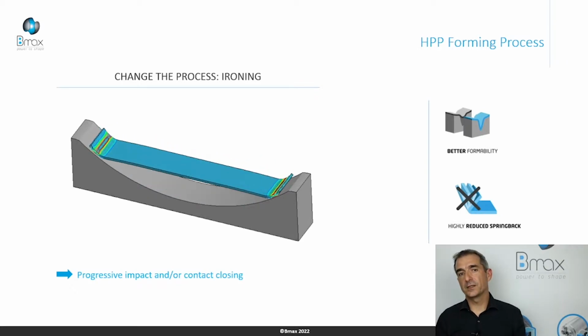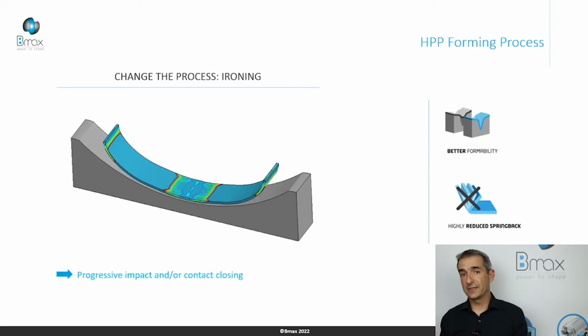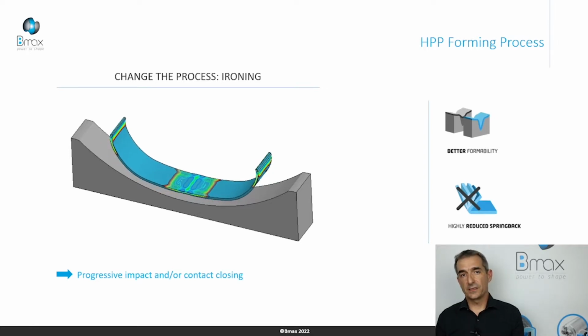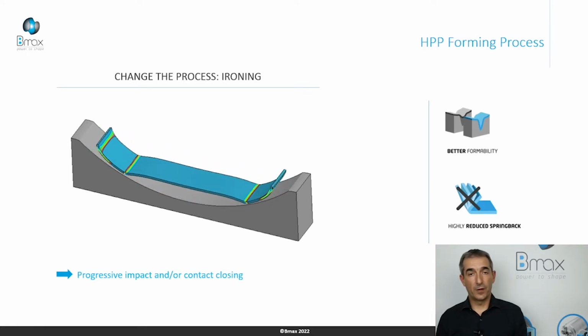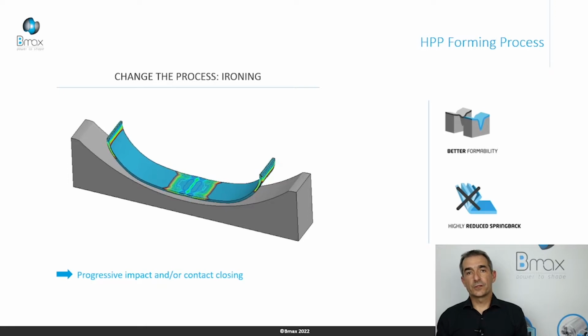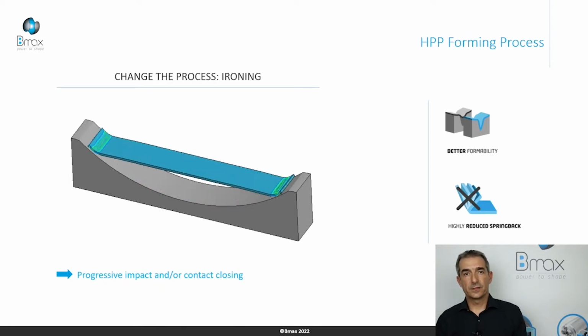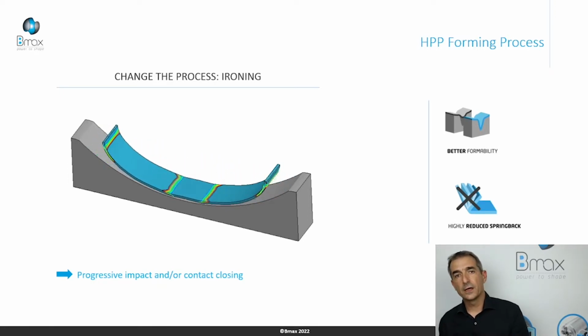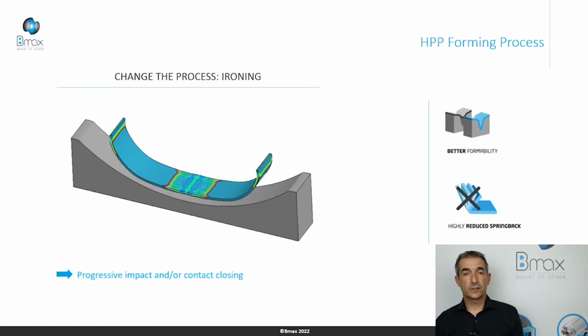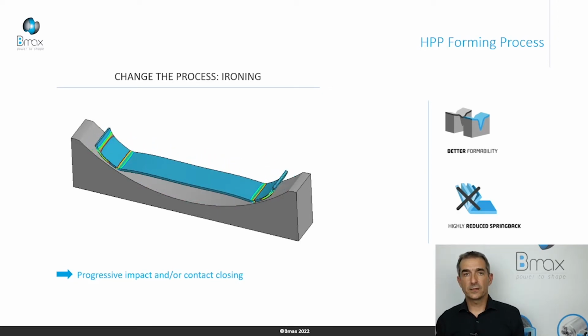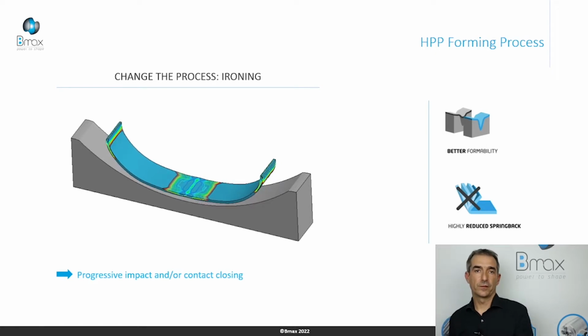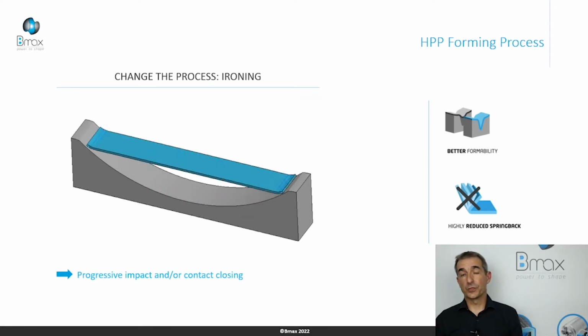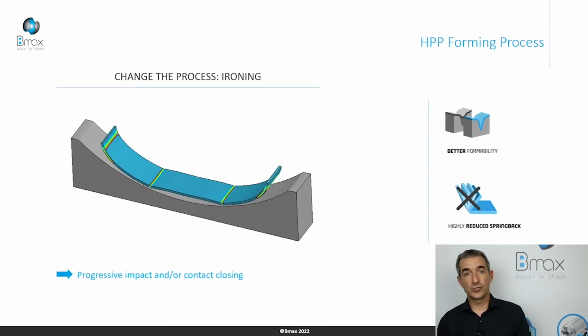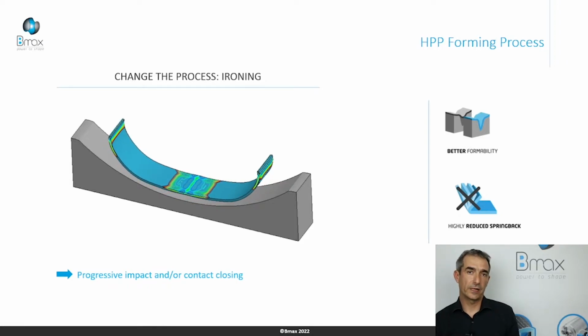And if we compare this test with a static bending test, at the end of the bending, we have an opening on the blank in static. The curvature of the blank is less important compared with the curvature of the die. And in dynamic, it's not the case. In dynamic, we have a closing of the blank. The curvature is higher compared with the die curvature. So it's very specific, and we change the process itself due to the impact.